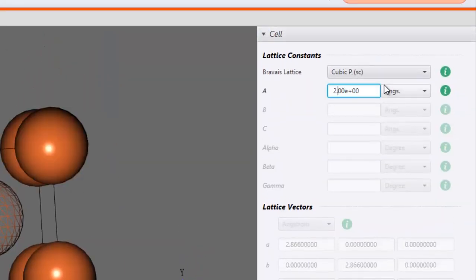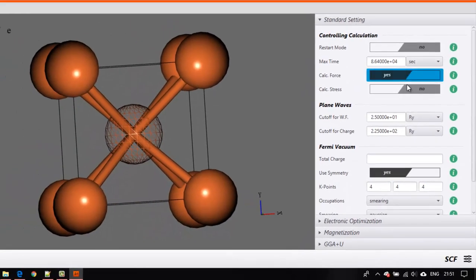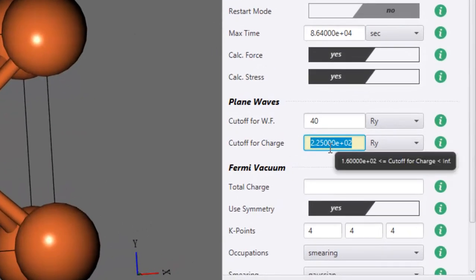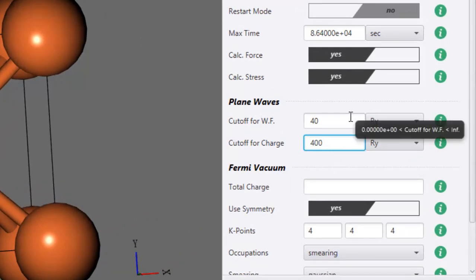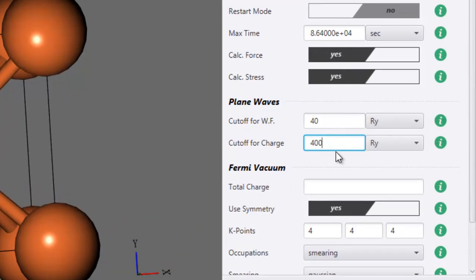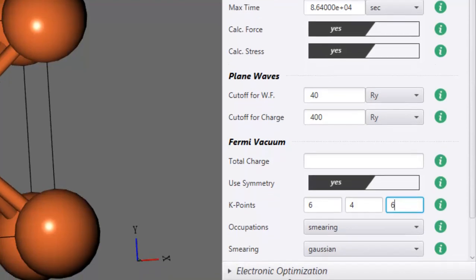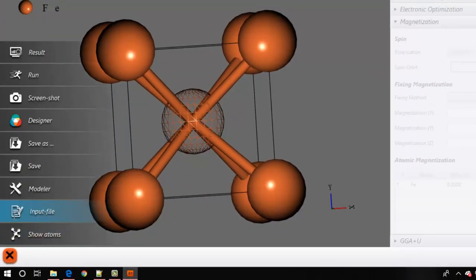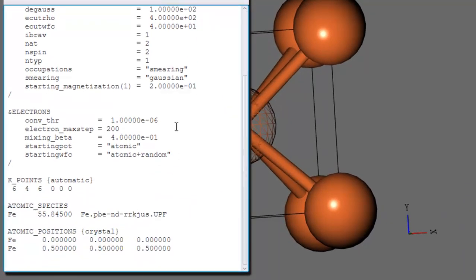Then change the lattice to 2.866 and go to the SCF settings. Change the options to yes, increase the cutoff to 40 Rydbergs — you should perform a convergence test, and I have already made a video about that. However, for this rough calculation we are taking 40 Rydbergs. Set the k-point mesh to 6×6×6, let the smearing be Gaussian, and magnetization is on. That is pretty much okay for a rough calculation.